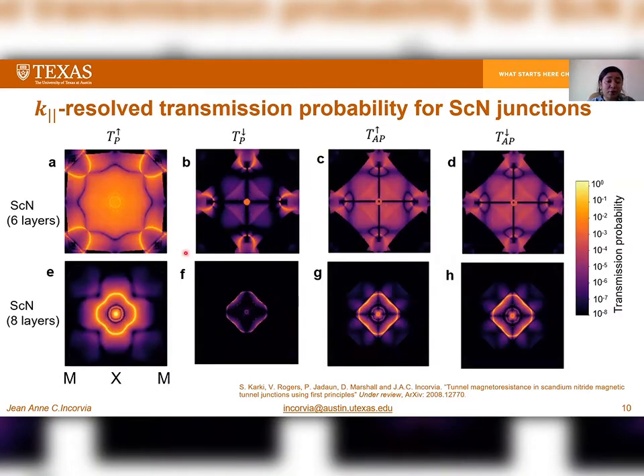So we looked at several k-resolved transmission probabilities for our junctions. The top A, B, C, D is for the 6-layer SCN, and the bottom E, F, G, H is for 8-layer SCN systems. Each one shows the up and down channel in the parallel configuration and the up and down channel in the anti-parallel configuration. As you can see in figure A, there is a lot of transmission around the gamma point and also around the M point, which is expected because we have a direct gap around the gamma point and also an indirect gap in SCN systems.